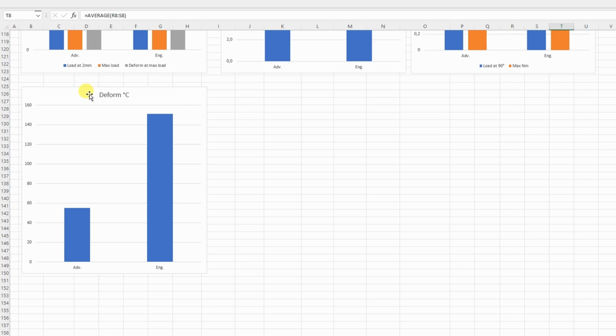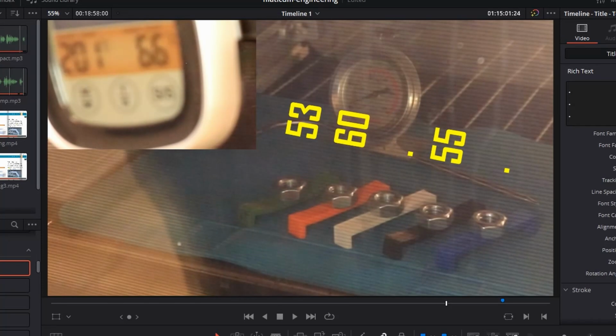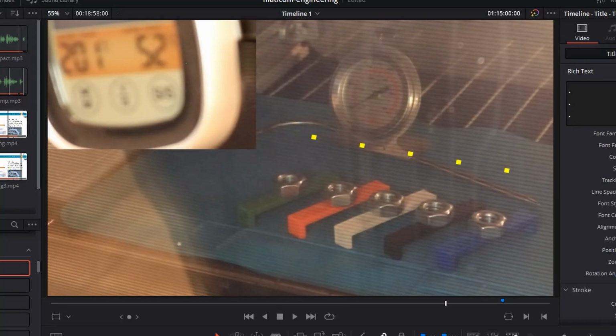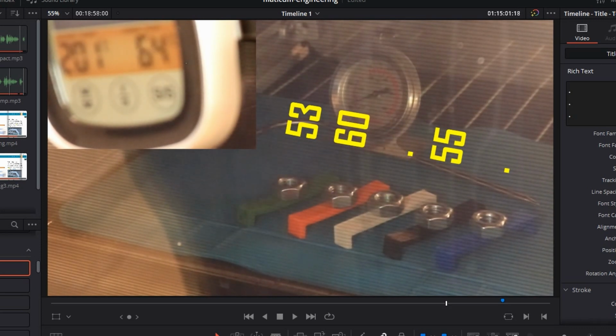And now this temperature test. I think this is the most important for these two materials in this video. The engineering PLA was very impressive. I noticed the start of the deformations at approximately 150 degrees Celsius. That's very impressive. Now about advanced PLA, the first deformation I noticed was approximately at 55 degrees Celsius, but then it slowed down with the deformations and actually deformed completely after the ABS deformed. Here you can see some repeated footage from that test.